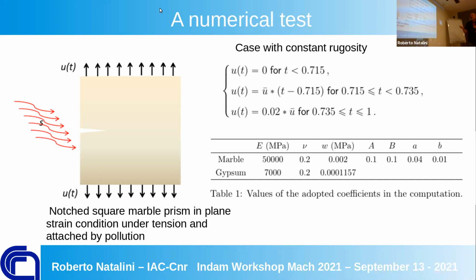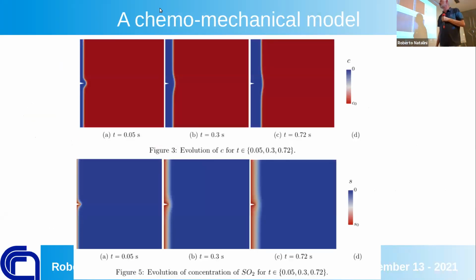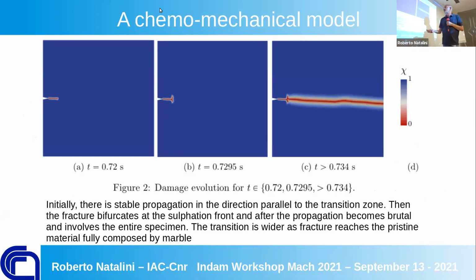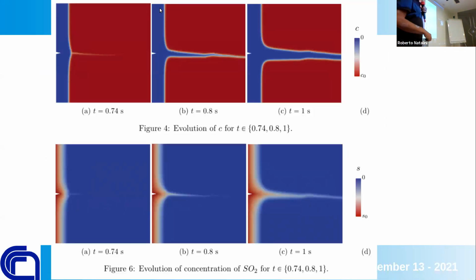and you apply this stress for some time, no stress before, sometimes 0.7, for instance, and then you have a linear stress, and then you have a constant stress after this time. And you see that at the beginning nothing happens, we just have the evolution of the crust, but there is no damage. But then after this time you are applying the stress, we have this kind of damage evolution, which is very fast. So we have a coupling, and a nonlinear coupling between these two different phenomena. Here, there's the change in gypsum and there's SO2, and here the change of gypsum. So according to this kind of nonlinear behavior, it's an acceleration of the damage flow.